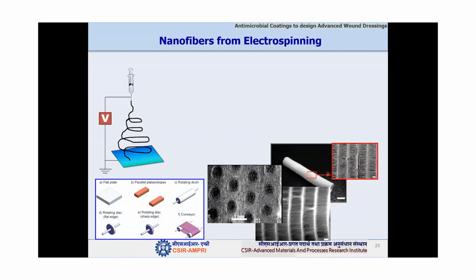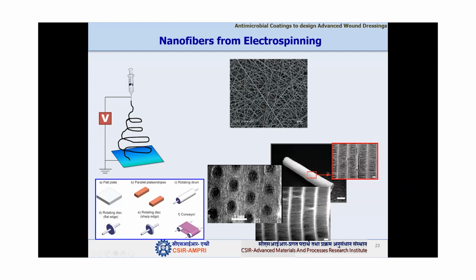You can see here the SEM pictures of the fibers. You can get the fibers in a particular orientation, in a particular pattern, by using different kinds of collector plates, like rotating collectors, parallel strip collectors, conveyors, rotating discs, or flat plates. So you not only get nanofibers, but also in a proper orientation, even aligned in a circular manner or in any kind of pattern. You can design these nanofibers using the electrospinning technique. You can see here the SEM picture of the nanofibers collected using the electrospinning technique.